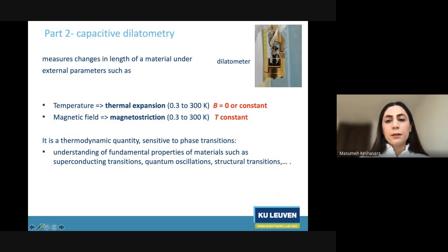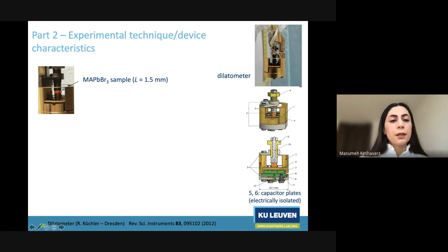On the right side, on the top, you see a picture of a dilatometer, or thermal expansion measurement. One can measure thermal expansion as a function of two different parameters, either temperature or magnetic field. Through these measurements, one can access information such as superconducting transitions, quantum oscillations, or structural transitions. Here you see a closer picture of the setup. It's very simple and user-friendly.